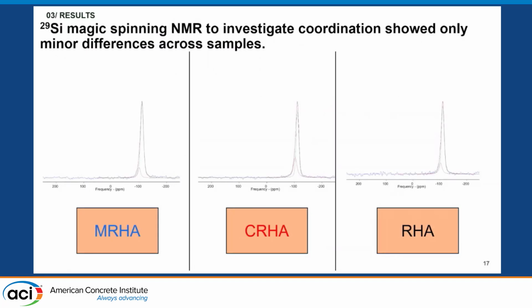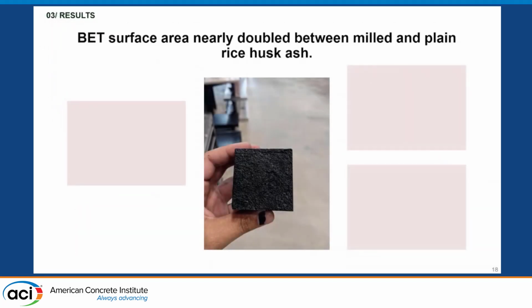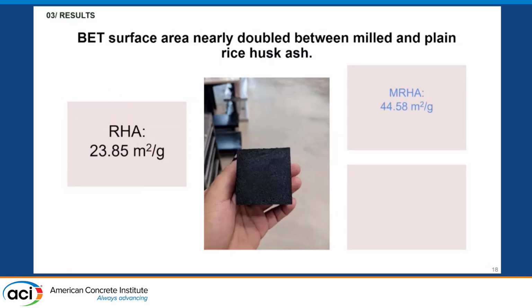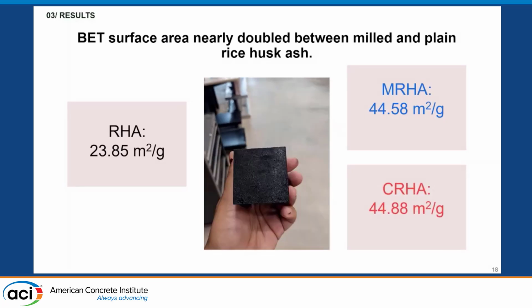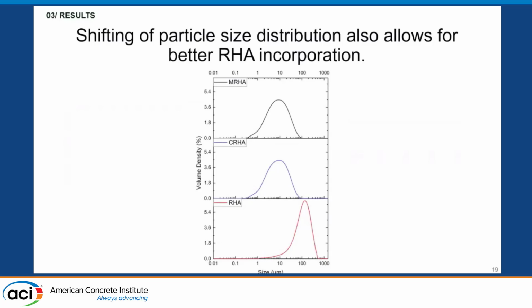And then I also ended up looking at the 29Si silica nuclear magnetic resonance just to see if there's any change in the coordination of the silica, which there doesn't appear to be much of, but this is something that I'm still exploring a bit further because there's a whole different side of things for NMR to kind of look at what the coordination is, and I have some future work related to that. But the surface area nearly doubles after that milling process, and so that is something that's very encouraging. We also have a shift in the particle size distribution, so that allows for a better incorporation into the